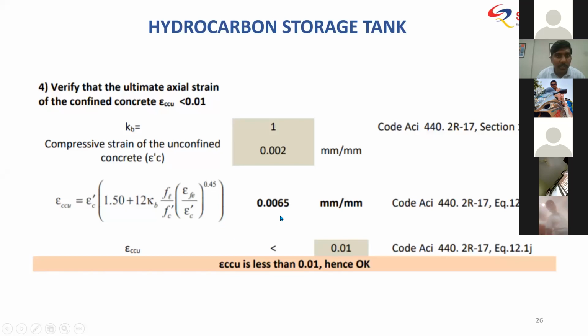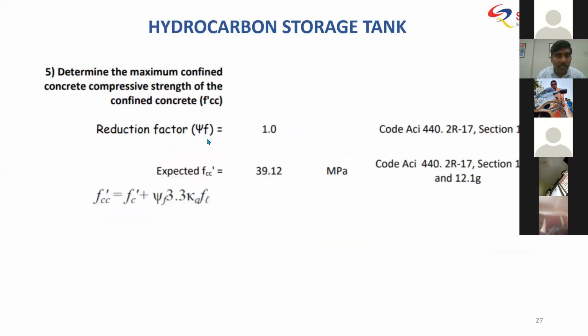So as per calculation, we were getting up to 0.0065, which is where we limit the FRP's strength providing capacity. And then there is another reduction factor, psi F. For circular, we can take it as 1. FCC dash is the ultimate strength of the wrapped concrete. Now, after application of the FRP, how much is the compressive strength of concrete? We found that after 4 FRP wraps, it has come up to 39.12 MPa from 29 MPa.